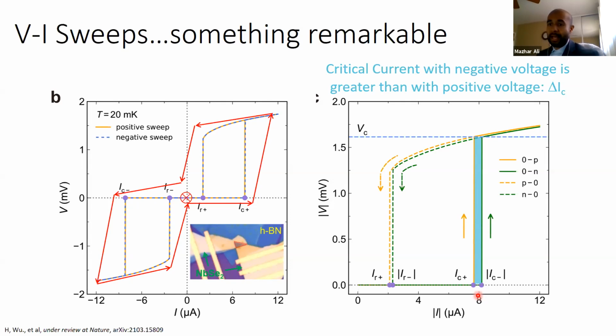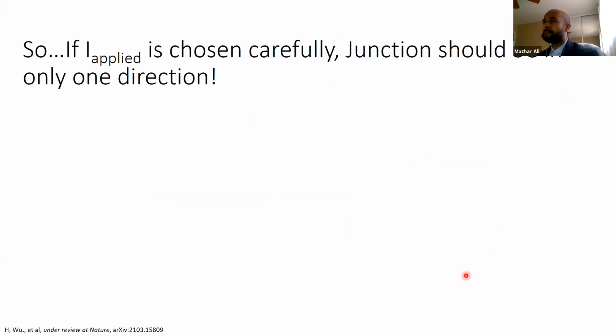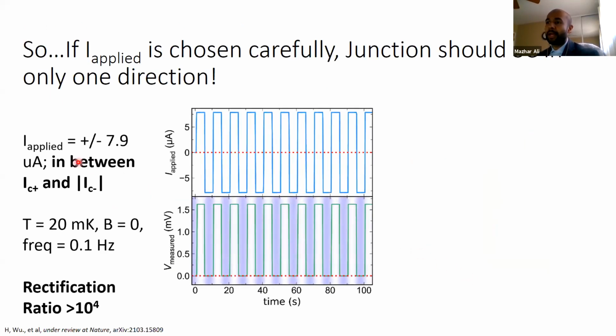And flip it, apply a square wave, and we should see it only superconduct in one direction and not the other. So Heng did that. He applied a 7.9 microamp, which is in between IC plus and IC minus. This is the applied wave. This is IC plus, this is IC minus. And you see on the positive side, we have a measurable voltage, as in a finite resistance. Whereas when we apply the negative current of the exact same magnitude, just a different sign, well, you don't. It's superconducting. And back and forth and back and forth.